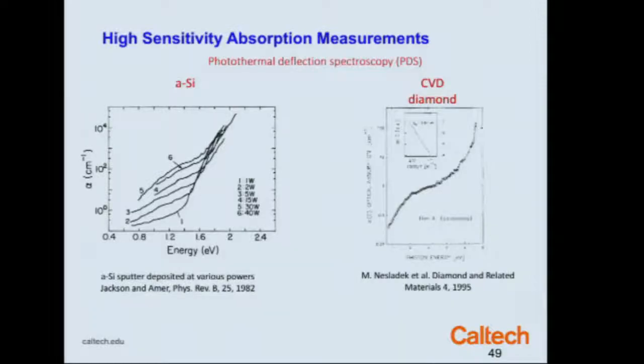So I won't go into this in detail. We have methods that were developed first at Lawrence Berkeley Labs and used actually to characterize the mirrors for the LIGO Michelson interferometer, called photothermal deflection and photoacoustic spectroscopy. They basically measure a temperature-induced refractive index, and they can make measurements of refractive index that are a couple of orders of magnitude more sensitive than we can by ellipsometry or conventional transmission measurements. And so these measurements have been made for diamond and silicon.